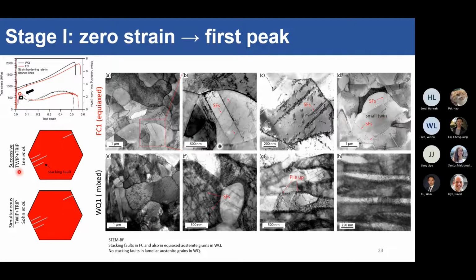So this is what the literature says you should be forming. If your austenite was deforming by the successive method, then you form some stacking faults here. If your steel was deforming by the simultaneous method, then you still have some stacking faults, but they will be different later on. So in the water quench sample, you can see that also you have some stacking faults in the slightly more rounded austenite grains, but in the lamellar austenite grains, what you have is dislocation pileups and also dislocation generation at the lamellar boundaries. Not a lot of stacking faults going on in there.